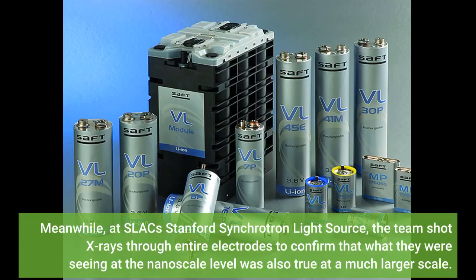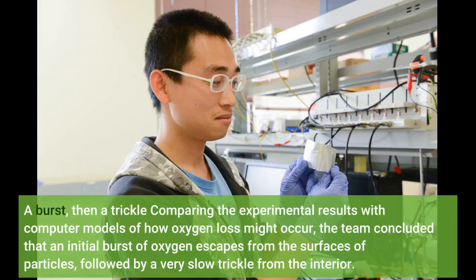This information was combined with a computational technique called ptychography to reveal nanoscale details, measured in billionths of a meter. Meanwhile, at SLAC's Stanford Synchrotron light source, the team shot X-rays through entire electrodes to confirm that what they were seeing at the nanoscale level was also true at a much larger scale. A burst, then a trickle: comparing the experimental results with computer models of how oxygen loss might occur, the team concluded that an initial burst of oxygen escapes from the surfaces of particles, followed by a very slow trickle from the interior.